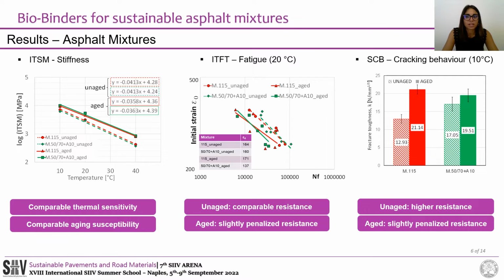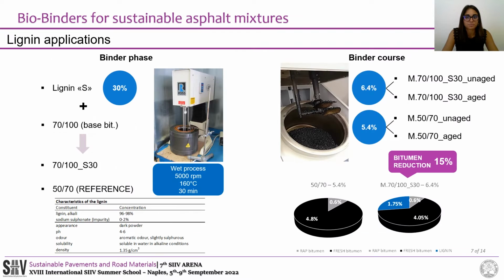Finally, from the cracking analysis, the bio-oil-based asphalt mixture showed higher fracture toughness in unaged conditions, but the higher resistance is not confirmed after aging.